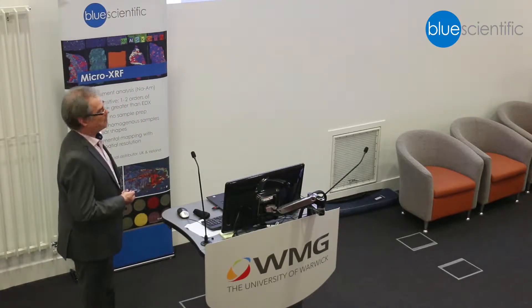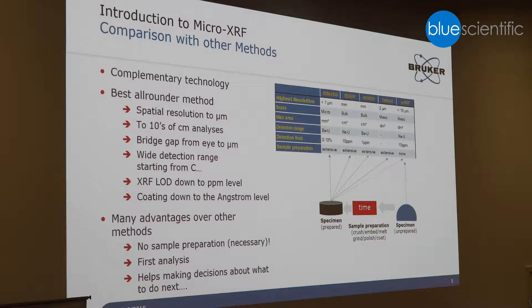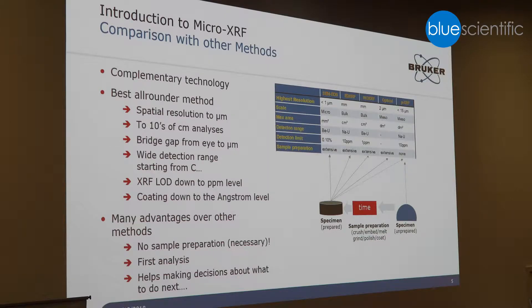Comparing methods: for Micro XRF, no sample preparation is necessary. For EDXRF or SEM EDS, sample preparation is involved. In terms of scale, Micro XRF goes down to the 10–20 micrometer range, while electron microscopy goes below 1 micrometer. For element detection, electron microscopy with electronic excitation can start from beryllium, while EDXRF usually starts from sodium — though our new instrument overcomes this limitation. For mapping, Micro XRF can map areas up to 20 cm × 15 cm, whereas electron microscopy has significant limitations.